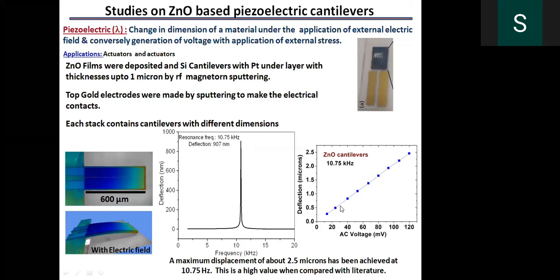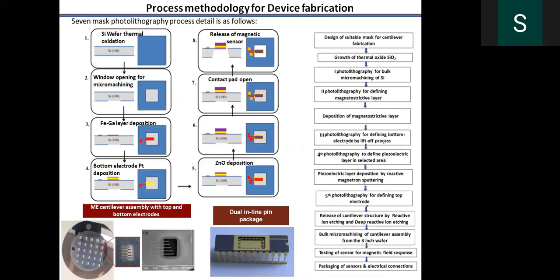The variation of AC voltage with respect to deflection shows a 2.5 micron deflection in this case. So now what we have done is we have integrated these two things by adopting a 7-mask lithography process. The 7-mask lithography process is something like that.